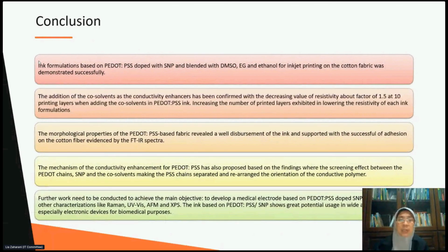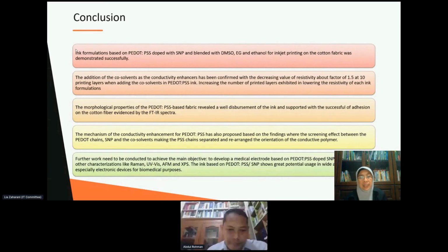So the conclusions from our research, we can see that the formulation based on PEDOT:PSS doped with SNP and blended with the DMSO, EG, and ethanol for inkjet printing on the cotton fabric has shown successful printing. So the addition of the co-solvent as the conductivity enhancer has been confirmed with the decreasing value of resistivity by a factor of 1.5 at 10 printing layers.